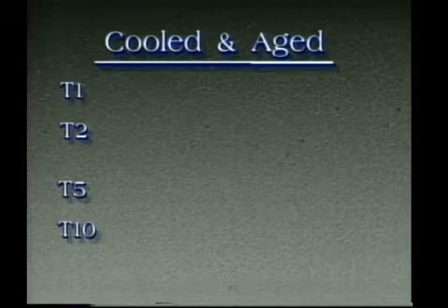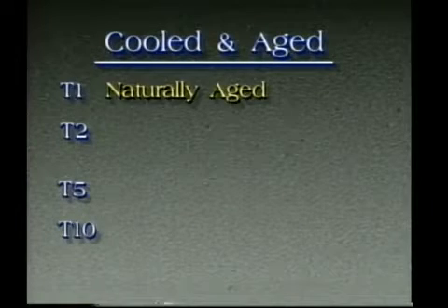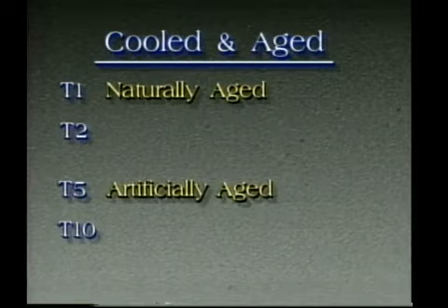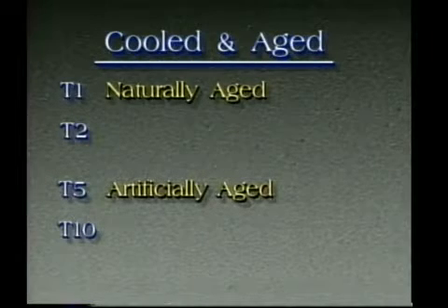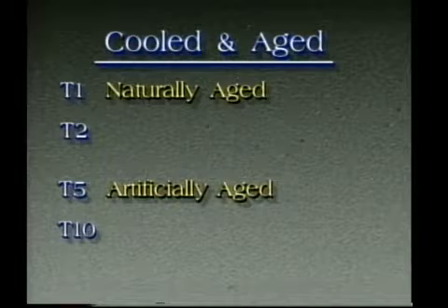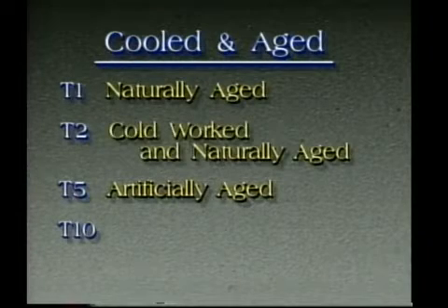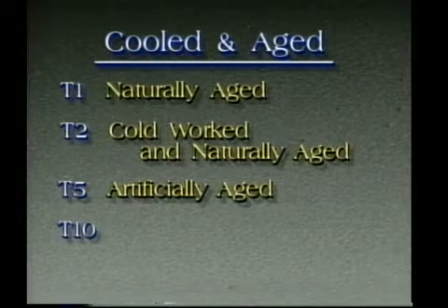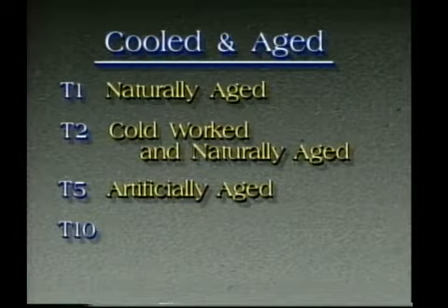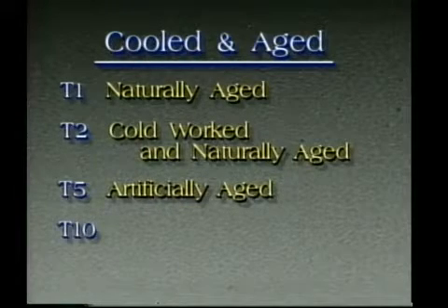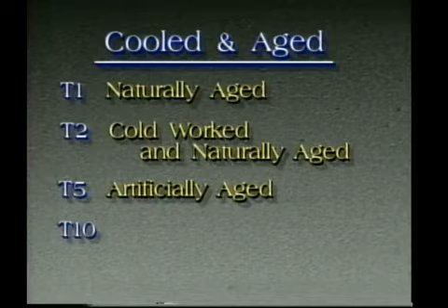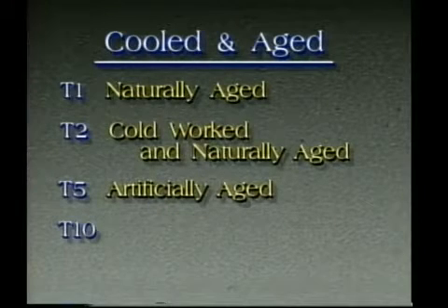The differences between them are as follows. The T1 temper is naturally aged. The T5 temper is artificially aged. T5 is used mostly for extrusions and castings. The T2 temper is cold worked and naturally aged. Previously, it was used as a designation for an annealed condition for cast products, but now is rarely used.